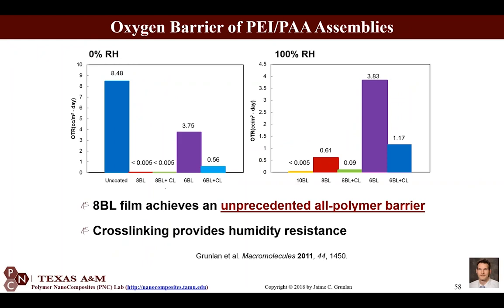So now here is without any clay. Now this is 600 nanometers, and I needed only 50 nanometers with a clay film to get that same high barrier, but it's just demonstrating once again the power of these ionic interactions. And there's also hydrogen bonding in this case as well. But anyway, there's such strong interaction between these polymers. And then once you cross-link it, we can maintain this very high barrier even at 100% relative humidity. In fact, that 10 bilayer film is not even cross-linked, and it's about 1 micron thick, and it's undetectable gas barrier even at 100% relative humidity, which could be great for something like food packaging.